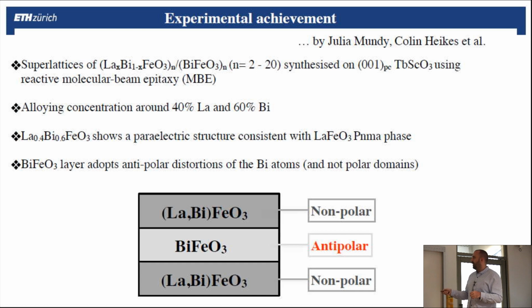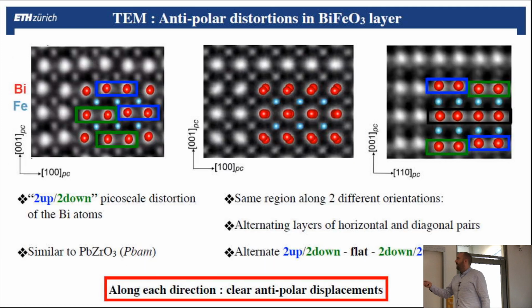They observed that building this heterostructure, the bismuth ferrite layer goes to an antipolar phase, meaning some atoms moving in one direction, some atoms in the opposite direction, which would result in no net polarization. So let's have a look at what they observed experimentally on this layer of bismuth ferrite surrounded by this. So now we'll zoom on this layer. And this is what you can see here.